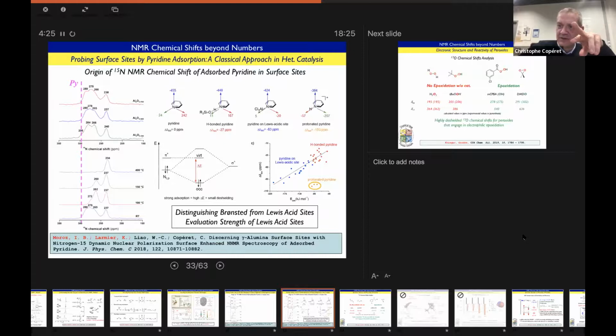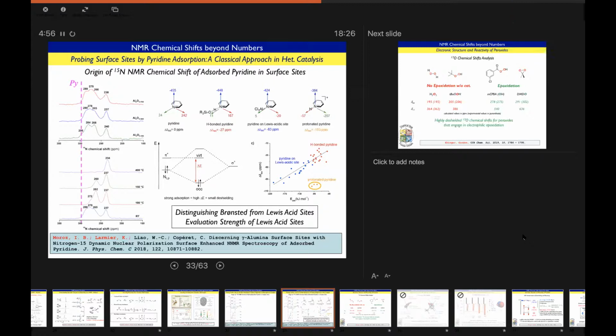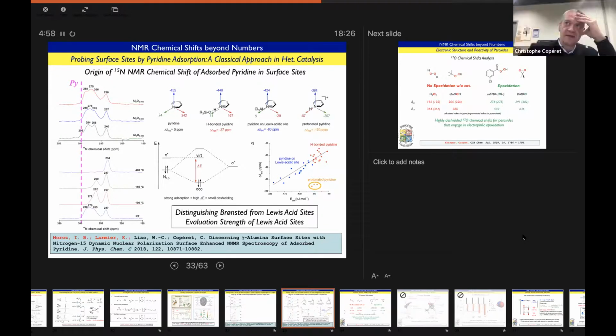But I would say the analysis for the NMR of paramagnetic material is a bit more convolved, because you have not only the anisotropy coming from the effect of the electron on the nuclei, but also the pseudo contact shift and the contact shift. That makes it a bit more complicated. And I think calculations are not yet at the level where you can trust them. I don't think it's possible yet to analyze NMR as we can do with natural chemical shift analysis.